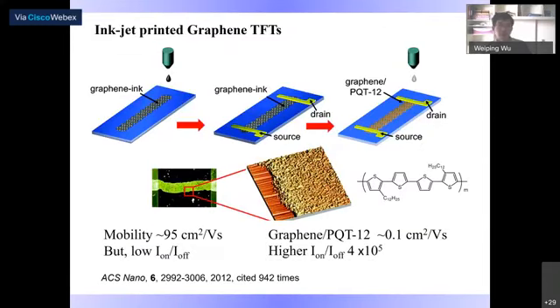Another challenge of using graphene for transistor devices is that it has zero band gap, so we can't get a high on/off ratio using zero band gap graphene as the channel material. By hybridizing with a semiconducting polymer, PQT12, I managed to improve this on/off ratio significantly while maintaining a high level of mobility. This paper was published in ACS Nano, and the citation count so far is more than 900.